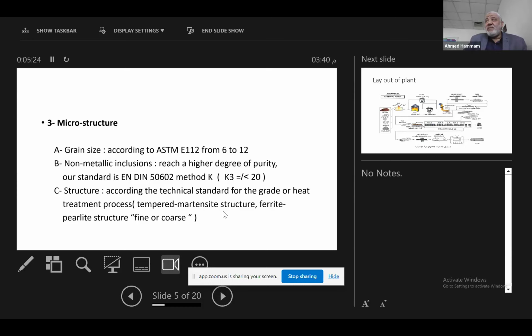The second part of the microstructure is the non-metallic inclusions, which should be of a higher degree of purity. We are keeping the K3 standard approximately equal to or less than 20. The structure should be adjusted even during the production on the line itself, or afterwards by heat treatment, in order to keep the desired microstructure with the desired grain size.